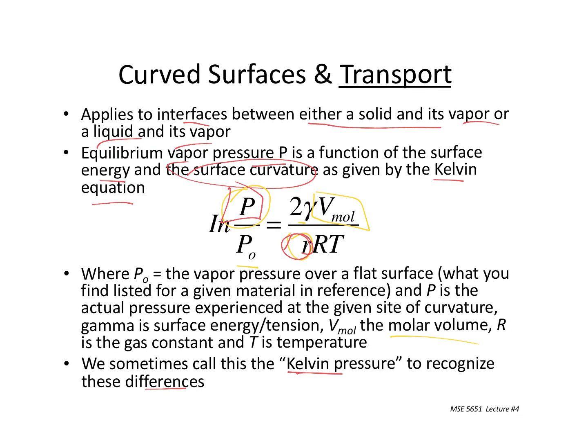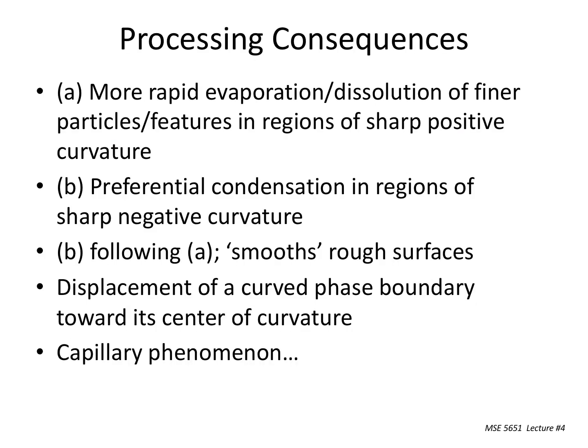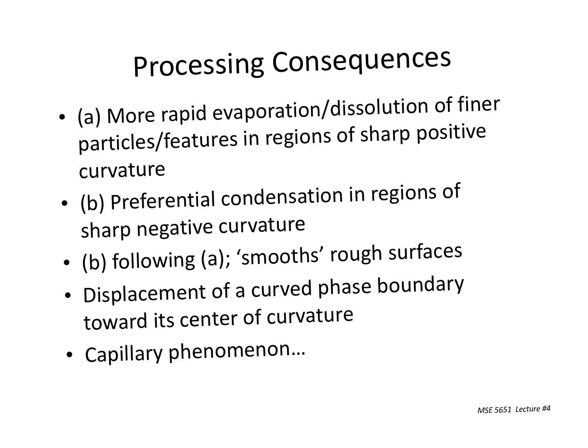Again, as I said earlier, you want to go back and think over these things. And so what does this mean? It means you'll get more rapid evaporation or dissolution, which relates to liquids, of finer particles or features in regions of sharp positive curvature, i.e. tiny particles or jaggedy peaks on top of a larger particle. It also means, as I mentioned earlier, you get preferential condensation in regions of sharp negative curvature. It means they want to fill up the concave surfaces. And the sharper the concave surfaces are, the more they want to fill them up because the pressure is lower there. And so this causes smoothing of rough surfaces.